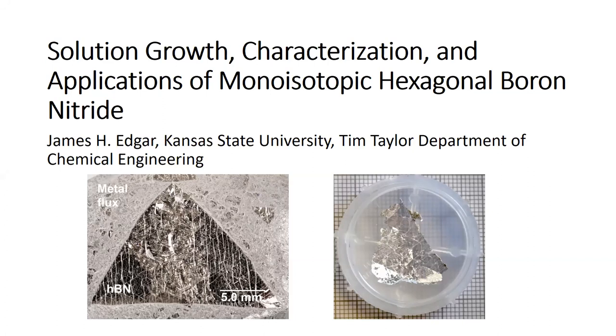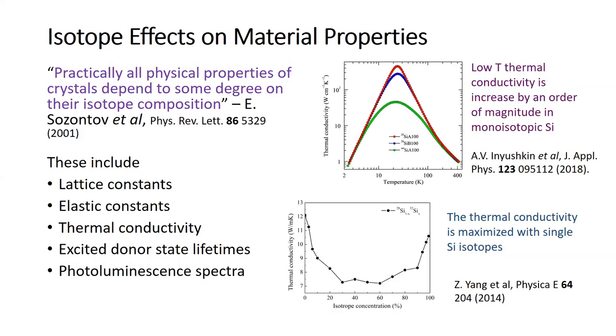So I'm going to talk about solution growth of boron nitride, and the first thing I should point out is this is one of the crystals we've grown on a metal, and then we exfoliate it. It's a pretty good size for a freestanding piece of boron nitride, maybe 10 to 20 microns thick and a couple centimeters across. So the question might come up is, why would you be interested in varying the isotope concentration?